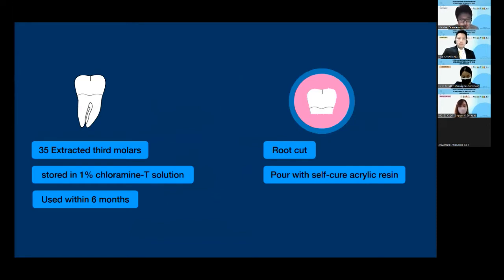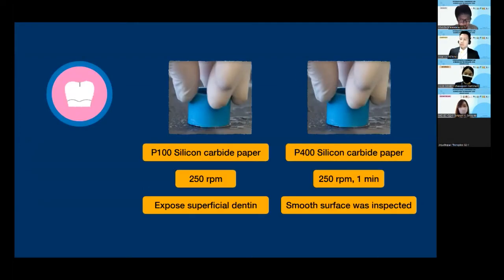35 extracted human third molars were collected and stored in 1% chloramine-T solution. The teeth were free from caries, restorations, and previous endo. The teeth were used within 6 months after extraction. The roots were cut and placed in the PVC mold, then self-curing resin was poured in the mold. Then the dentin surface was prepared according to ISO 29022:2013 by a 2-step sequential grinding process using P100 silicon carbide paper to expose the superficial dentin, followed by P400 silicon carbide paper, then cleaned the surface with an ultrasonic cleaner in distilled water for 10 minutes.